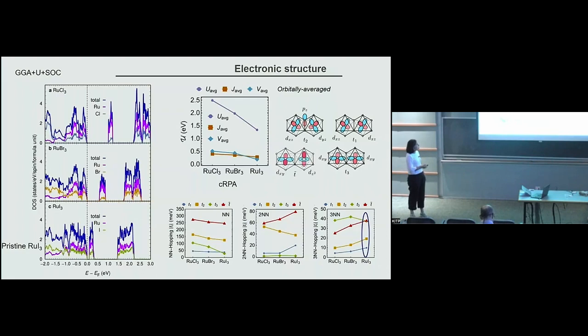So what I'm showing here is an analysis of the electronic parameters, just to see the evolution of the Coulomb repulsion as well as the Hund's coupling as a function of going from chlorine to bromine and iodine, so how they change due to the fact that you also have these halogens, especially iodine, that has a strong spin-orbit coupling. And let me just point out here that the longer range interactions or hybridizations get more and more important in the iodine, due to the fact that iodine is very big. So you are going to have longer range interactions.